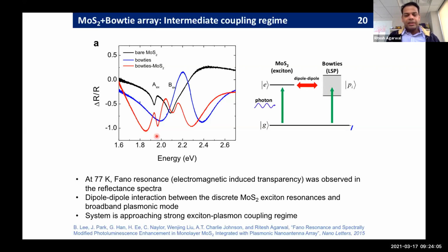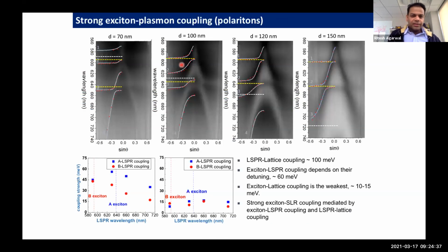This is the Fano resonance, where you have a two-level system coming from the exciton, let's say, a dipole coupled to a continuum of plasmons. So you have two initial states and two final states, direct excitation of the exciton or via the plasmons, and then there's interference between these two pathways, leading to this effect. So this set up the agenda which we're still following until today, and that is, can we now push the system to strong coupling limits, where we can create exciton plasmon polaritons in these systems? And the answer is yes.